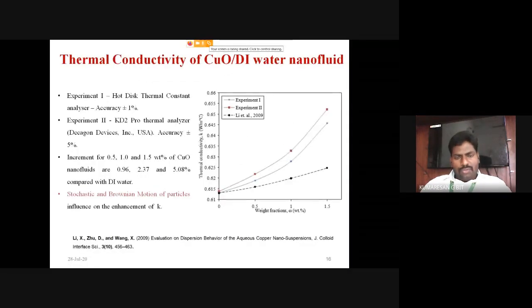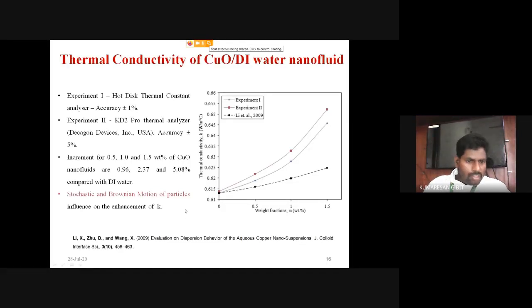Okay. The next one is the thermal conductivity of the nanofluid. There is the copper oxide DI water nanofluid. Here, I have used two different technologies to analyze the thermal conductivity of the nanofluid. The first experiment is done with the hot disk thermal constants analyzer, and the same experiment is repeated with the KD2 Pro thermal analyzer. Okay, both have an accuracy of 1% and 5%. Okay, here the increase in thermal conductivity for 0.5, 1 and 1.5 weight percent of copper oxide nanofluids is about 0.96, 2.37 and 5.08 percent compared with that of the base fluid. Then stochastic and Brownian motion of particles influence this. Yeah, so these properties influence the enhancement of thermal conductivity of the nanofluids.